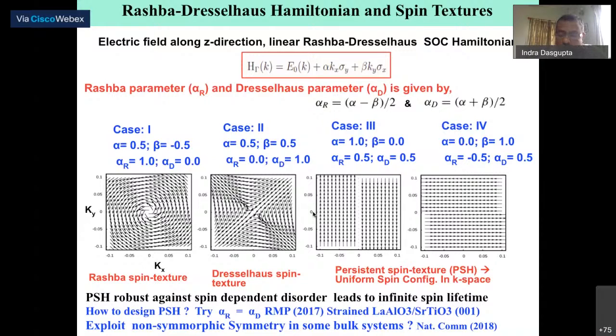Of course, one has to try with having alpha R equal to alpha D. For example, this has been possible in LaAlO3 and strontium titanate interfaces along 001 upon application of strain. But of course, managing and maintaining it becomes very difficult. So what people have also argued is that in certain materials, if you look at the symmetry, particularly non-symmorphic symmetry in certain bulk systems, then one can stabilize such persistent spin textures. So what I'm going to tell you today is under what circumstances you have Rashba or Dresselhaus kind of spin textures, and what you need to do symmetry wise so that you can stabilize persistent spin textures.